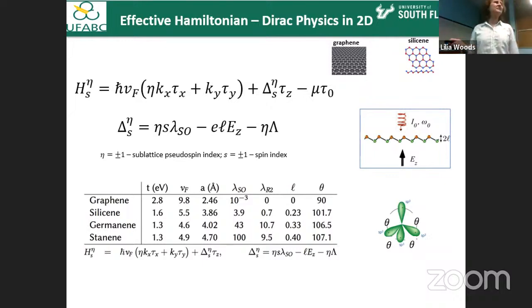And it turns out that we can write an effective Hamiltonian for the low energy physics of this kind of system. Graphene is flat, but silicene and everybody else in the periodic table are not flat, they're staggered. Because of the staggering, if I apply an electric field perpendicular to the sheet of the 2D layer, and I also apply a laser, we can control the magnitude of this energy gap.